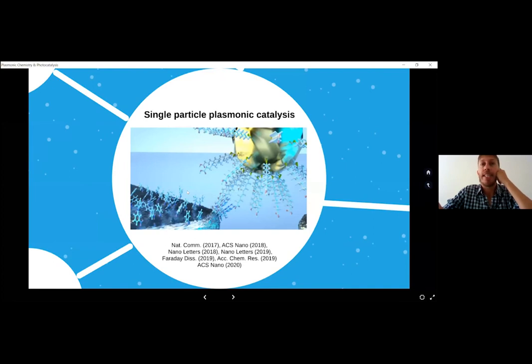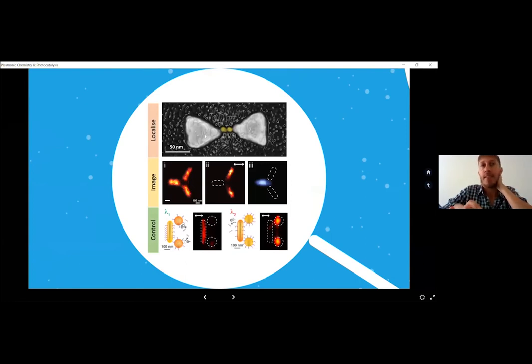So we did quite a lot of work in single particle plasmonic catalysis in order to try to understand these phenomena. And we developed some techniques, either based on electron microscopy or on super resolution microscopy, in order to track the chemical reactivity of these nanostructures. The first idea that we had when we started working on this was to localize the reactive spots on the surface of these plasmonic nanoantennas, so where the reaction is taking place. For that, we started with these silver bow tie antennas, these triangles here, and we used these really small gold nanoparticles in order to track where the reaction was taking place on the surface of these nanoantennas.